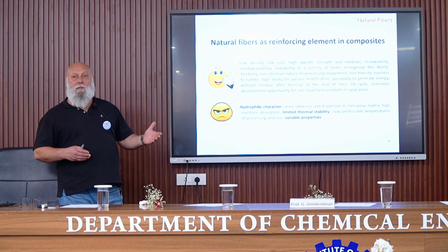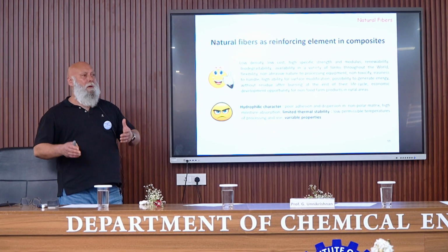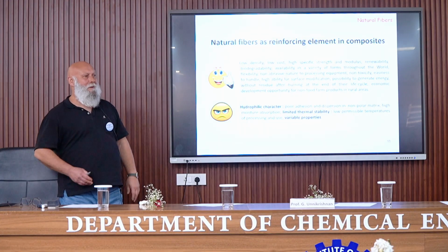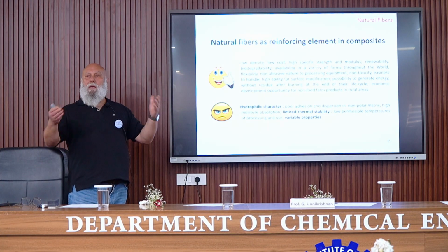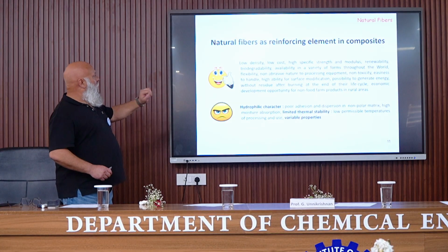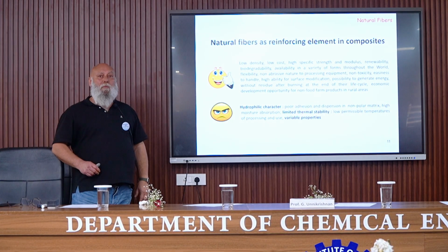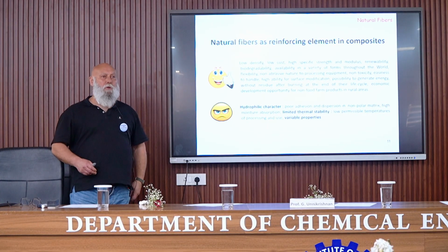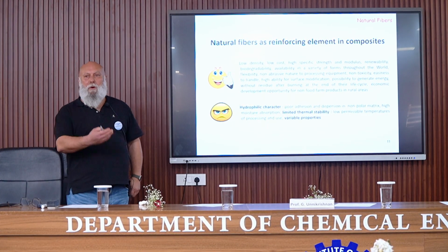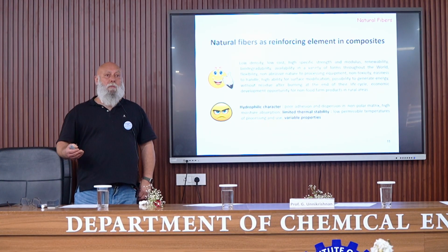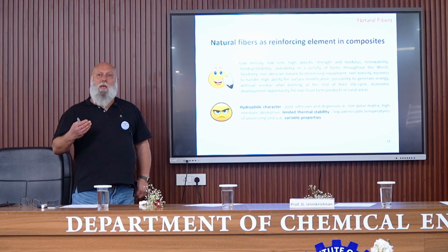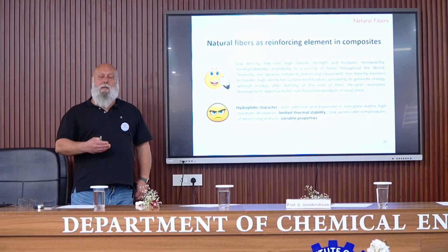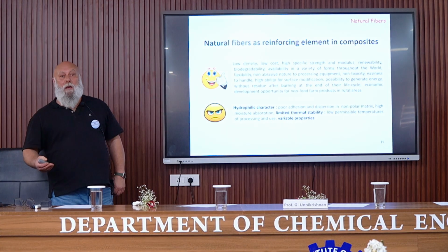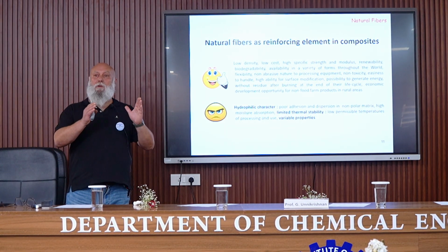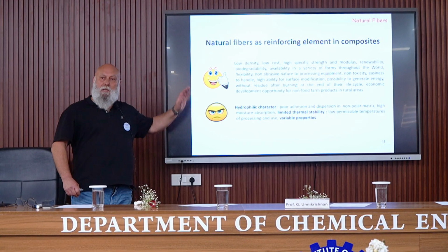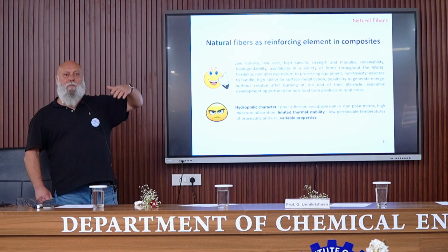For example, in France, it's mainly flax and hemp. I don't know exactly for India, maybe banana. But anyway, you can adapt depending on the local resource. These fibers are flexible, which is important because during composite processing, different equipment can be used, for example extrusion. During extrusion, high shear rates are applied to the material. When using glass fiber, of course, the result is a decrease in the length of the fiber, which is not the case with natural fibers because they are flexible.